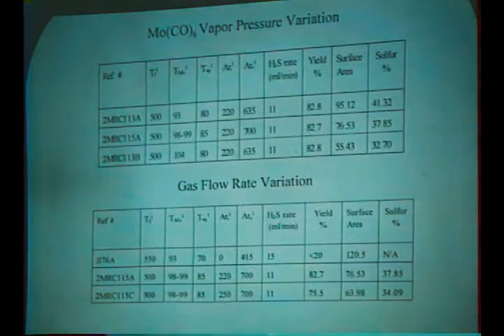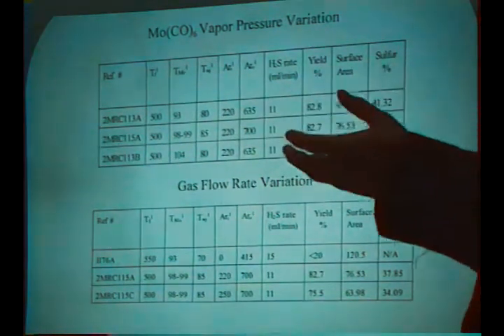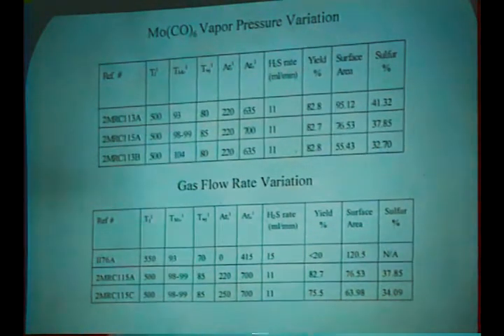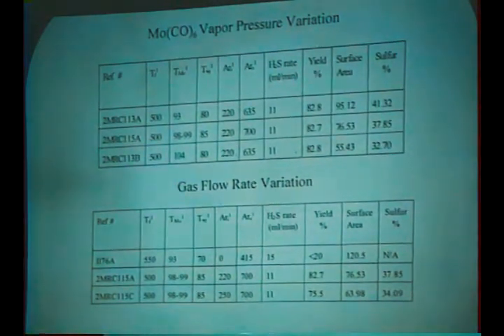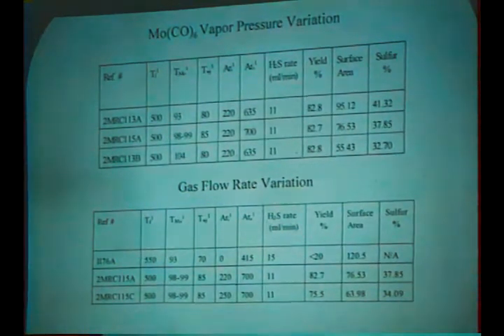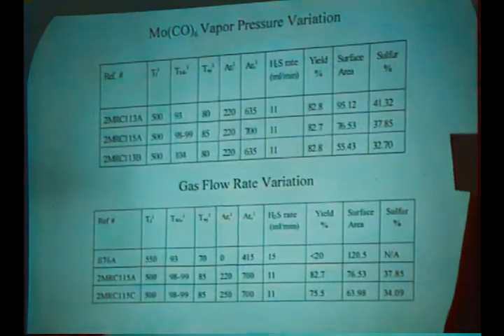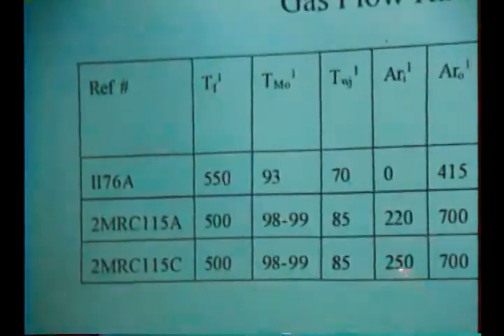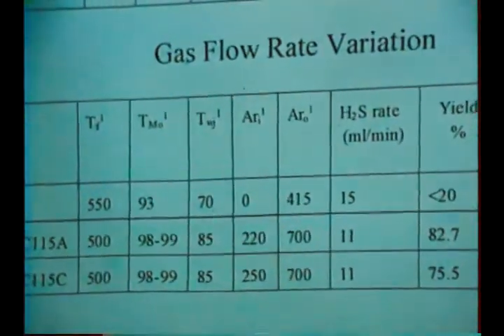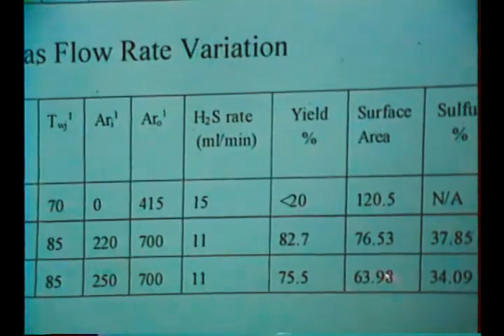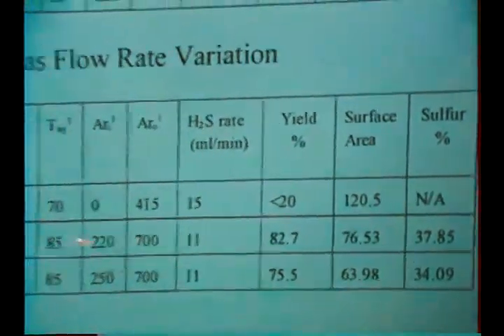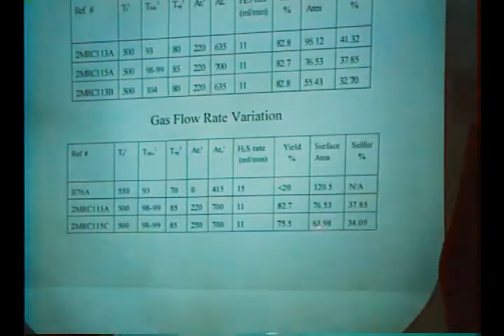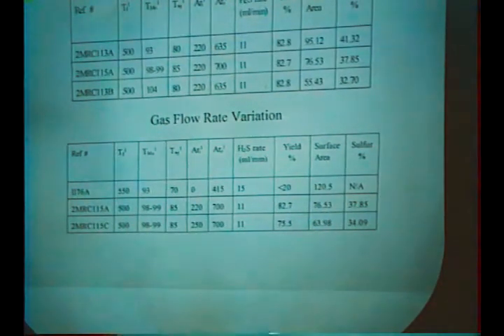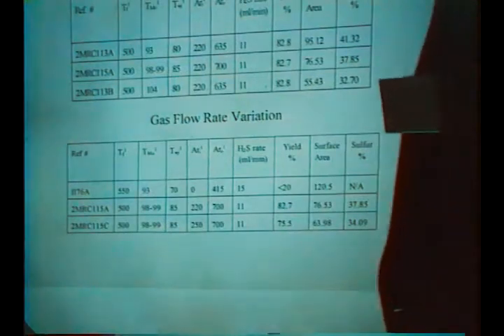Now, if the gas flow rate, that is the argon or the helium, is changed, we can look at here the effect of the argon. If you look at the argon flow rates here, going from 0 to 220 to 250, and the corresponding effect on the surface area starting at 120, going down to 63.98. So by increasing the flow rate, we actually increase the flux of the molybdenum carbonyl through the system, and necessarily lower the surface area. And again, the sulfur percentages drop as well as the flow rate is increased, or as the concentration of the molybdenum carbonyl is increased.